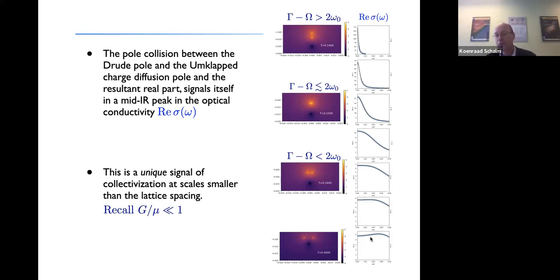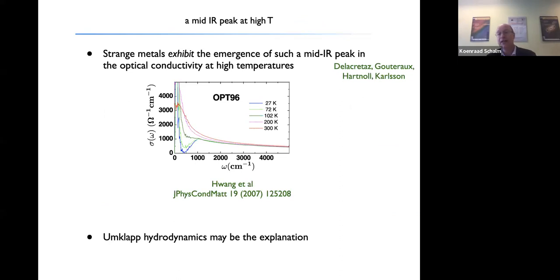Note that this is very different from Goldstone pinning, where precisely you get that this peak moves off zero frequency as you lower the temperature in the system. And that's precisely what I mentioned before. It's precisely this funny mid-IR peak that arises as the temperature is increased, which is seen in real experiment, and Umklapp hydrodynamics may be the explanation of this. In a certain way, you might say this is a first signal that you have hydrodynamic transport in strange metals. That may be pushing it a bit far, but it's certainly a case that you can make.